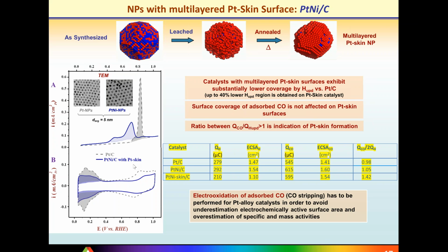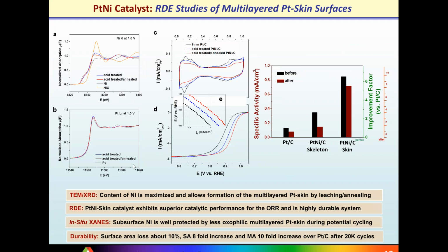So going back to this multi-layered platinum skin, you can see here a summary of electrochemical analysis and also in situ structural analysis by XAS, and finally a summary of activity and durability studies. So not only are those surfaces extremely active, and this is almost a factor of 10 compared to platinum carbon catalyst, but they exhibit extremely high durability due to that desirable skin, which is probably very close to a (111) type of surface structure. So in other words, here we were able to achieve both, to address activity and durability.